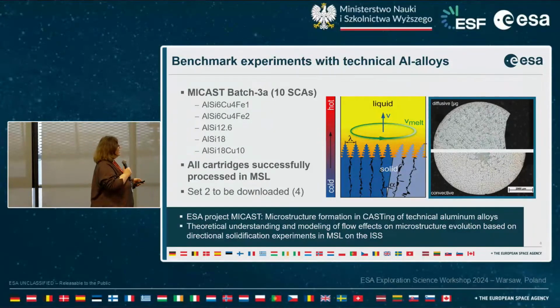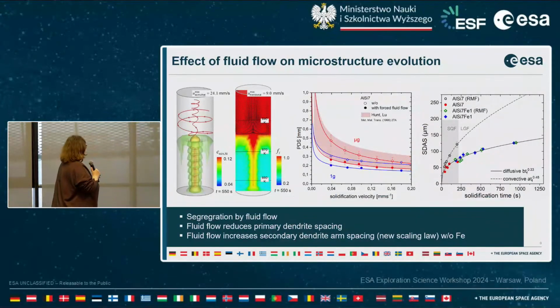see the strong segregation in the sample center. Our colleagues in Leoben can now model these fluid flow structures and also the reaction of the overall structure of the interface with these fluid flow conditions, so not only in 2D, but of course in 3D. And what you see here also is that the rotating magnetic field segregation creates a more or less liquid channel in the sample during solidification, enriched in this case with silicon.